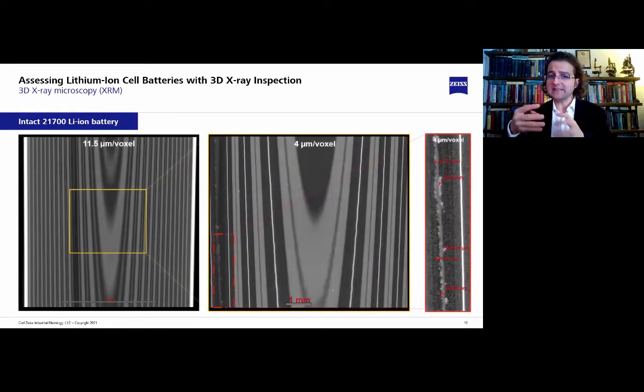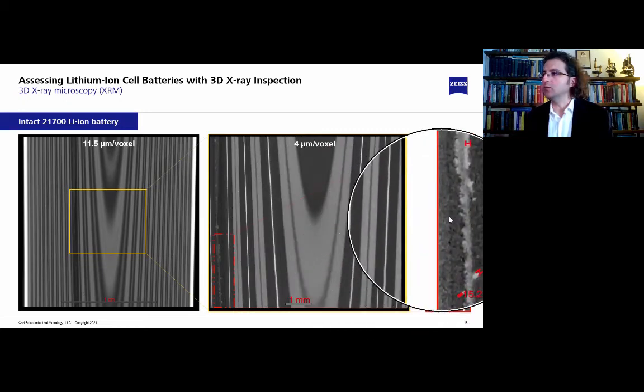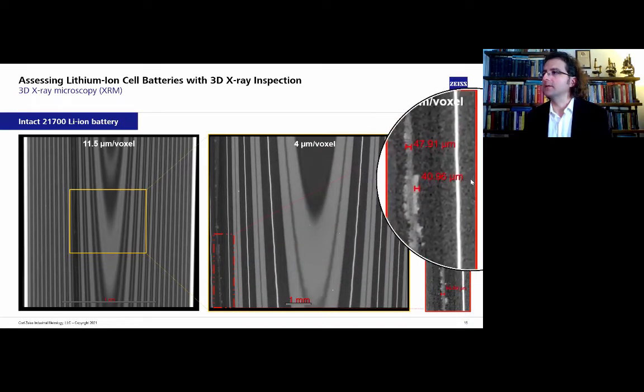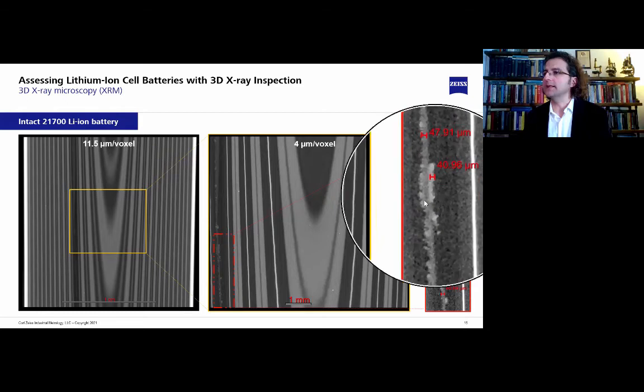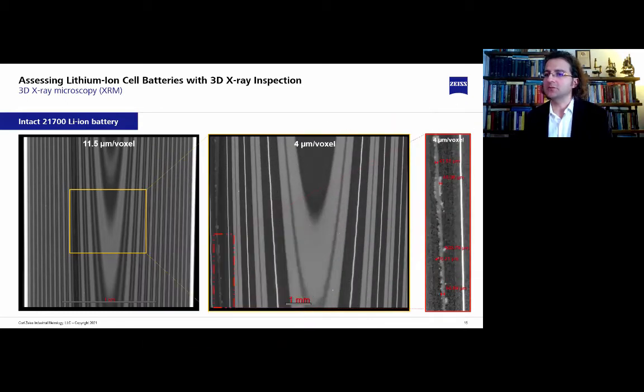In this image, you can see details not only at high resolution, but also at high contrast, which is often difficult to obtain with the traditional X-ray CT technologies. This is not a problem when you use 3D X-ray microscopes. And you can see low density features in the battery, such as the polymer separator layers that you can see right here. You can see the nice contrast of that image that comes from these regions of interest.